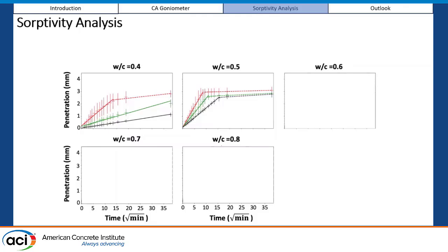Also, this is tested on an unmodified surface. If I sandblast the surface, the surface area of my sample becomes larger, so it will have more contact with droplets and expedite the spreading. I did test this, and I noticed that the samples should have roughly similar roughness. Otherwise, it's very difficult to get a good conclusion. Thank you very much. Thank you.